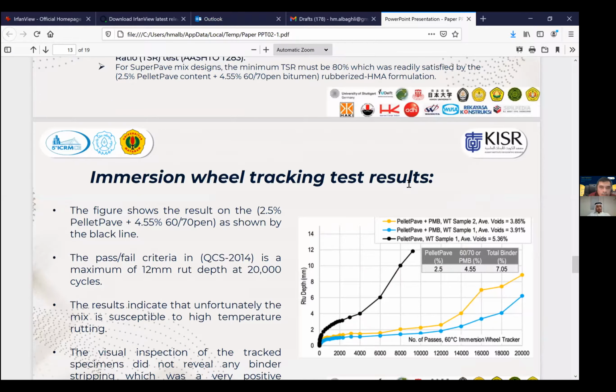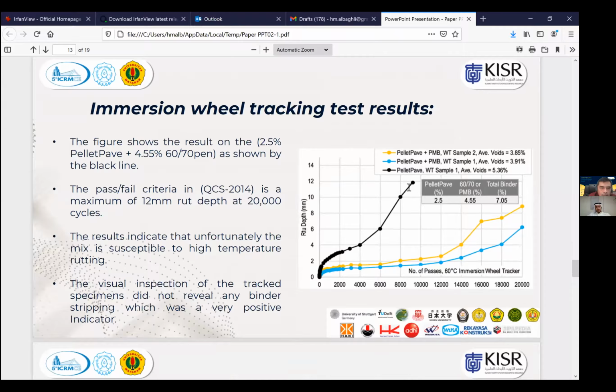black line. As you can see in this black line, it reached a 12 millimeter rut depth at almost 10,000 cycles. This means that the mix would not be ideal for medium to heavy traffic loads. It could be ideal for low traffic roads. However, visually, the tracked specimens did not reveal any binder stripping, which was a very positive indicator.